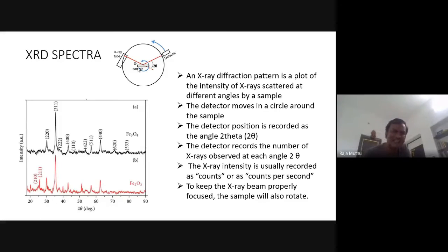The detected diffraction is this one for Fe3O4 and this one for Fe2O3. Right. So what is it? See, these are the indices: at the plane 220 the peak is observed. At 311, this peak is observed. At 222, this peak is observed. See here the 2 theta angle. For what 2 theta, what is the intensity? How much X-ray diffraction is obtained? At 20 degree 2 theta, there is no peak, only a smaller peak. But let us assume this is 25 degree. There is a peak. At 25 degree, the plane is 211. You will be getting this peak.